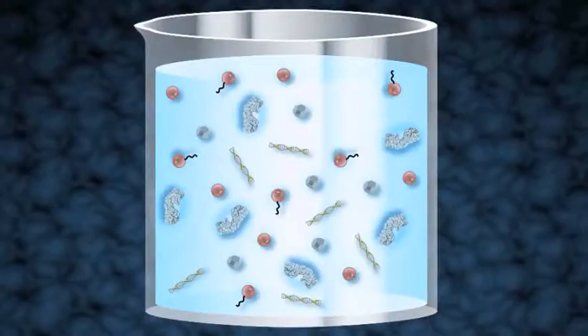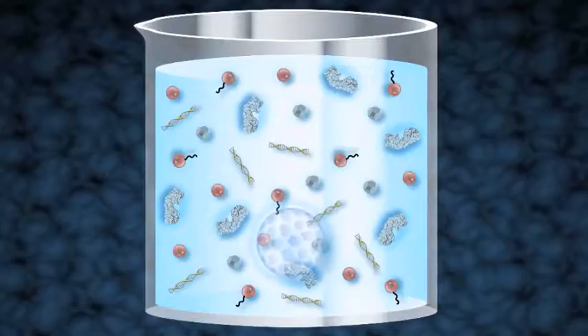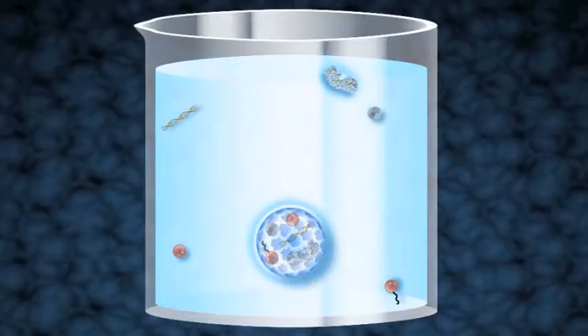And the center of that particle is essentially a sponge created on the nano scale, okay? And that sponge, if you put it into a beaker with your drugs, it will suck up the drugs into the sponge. And these particles that we make, if you can think about this, if I were able to unfold the nanostructure within them, I would get a carpet 10 meters wide and over 100 meters long with 1 gram of material. So this internal surface area sucks up and absorbs all these drugs. So that's sort of on the inside.